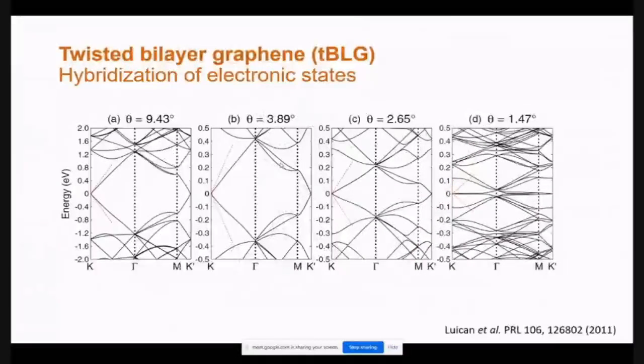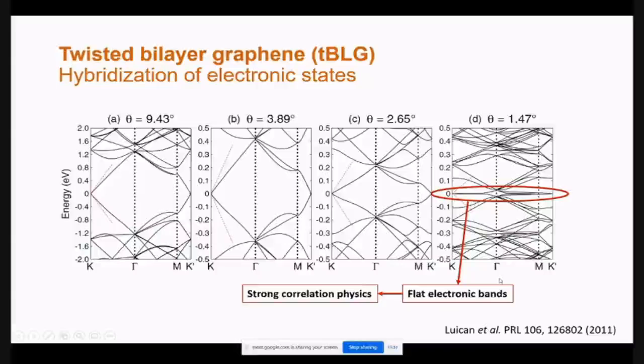The very interesting idea here is that when the angle between the two layers is large, for example 9.43 degrees, you can see the low energy structure is almost conical, like what happens in single layer graphene, which means that the two layers are essentially decoupled. However, as the angle goes down to about 3 degrees, the Fermi velocity starts decreasing. You can see the slope is decreasing further, and eventually at about 1.4 degrees, there's a magic angle, and you create what you call flat electronic bands, and that led to strong correlation physics, and so on and so forth.